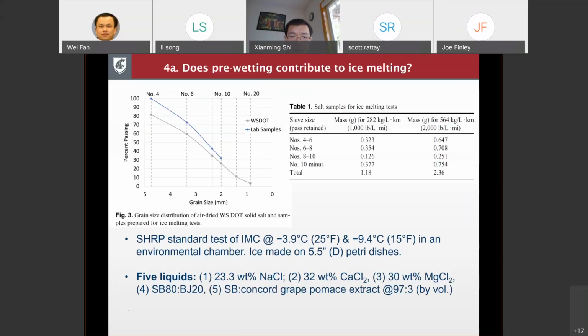So we ended up using a salt which is a little bit finer than the salt being used by the Washington State Department of Transportation, partially because if the particles are too large, the reproducibility will suffer. In the field, also because of the high volume and high speed traffic, the larger particles tend to be crushed anyway. So we're looking at salt particles finer than number 4 sieve, or 4.75 millimeter.